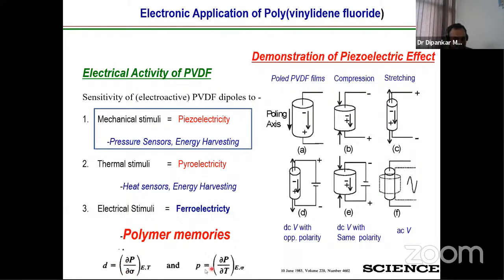So these two coefficients are very important. This is d, the piezoelectric coefficient. This is nothing but a thermodynamic relation. If we apply the stress, dσ, where sigma is the stress, the mechanical energy, right? We are changing the polarization when electric field and temperature are constant. Very simple, right? So piezoelectricity means if I apply the stress, we get a change of polarization when electric field and temperature are constant. Similarly, for the pyroelectricity, if we change the temperature, then we create a change of polarization when electric field and stress are constant. These two coefficients are very important in order to describe the piezoelectricity and pyroelectricity.